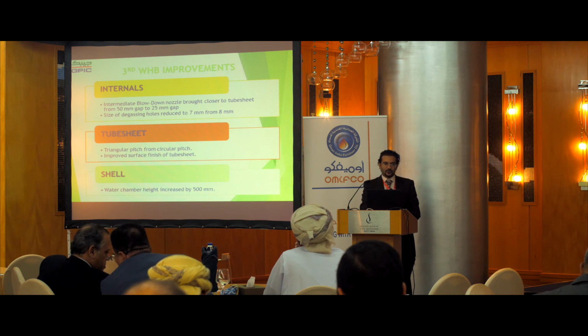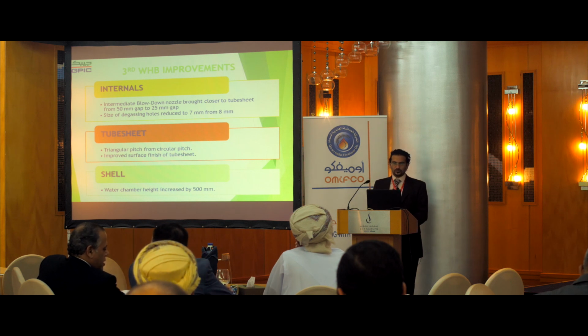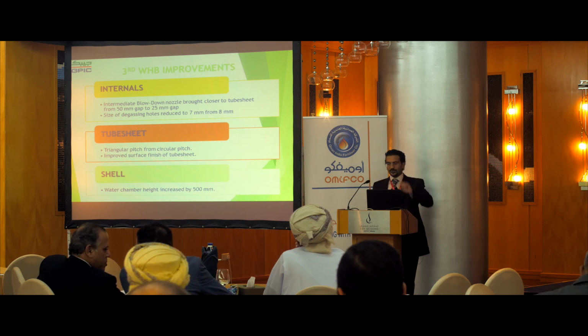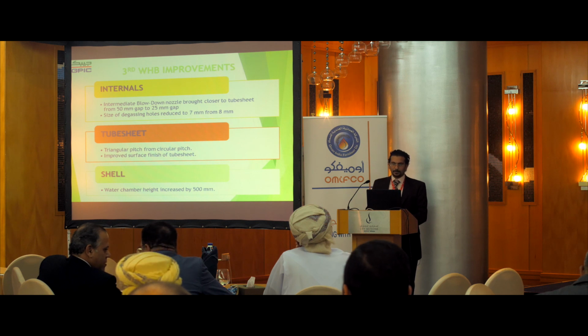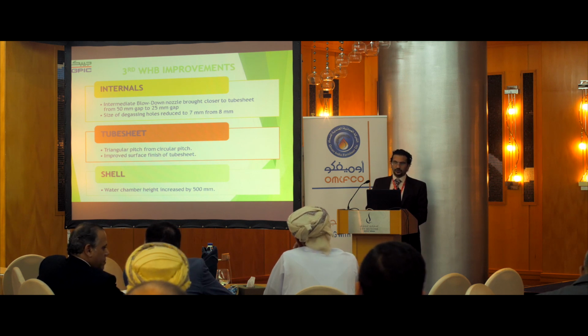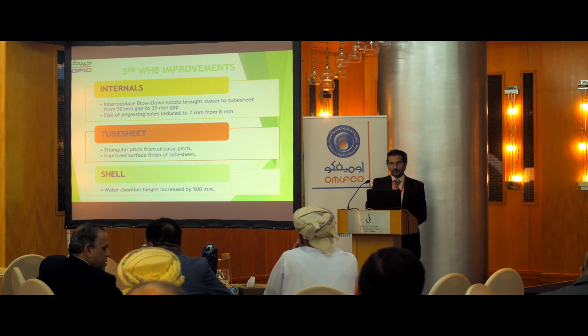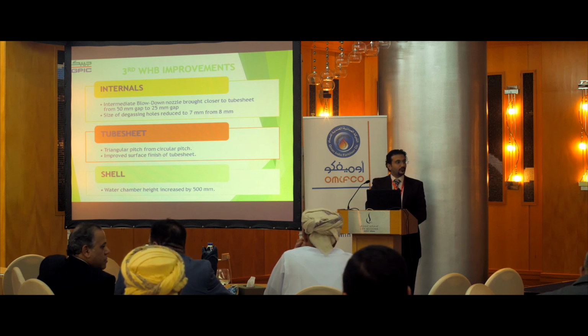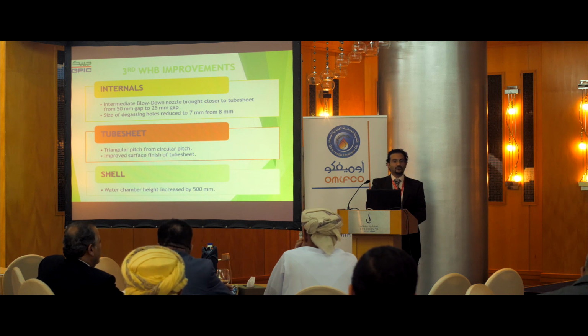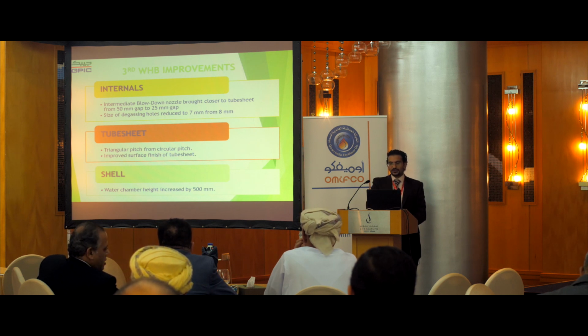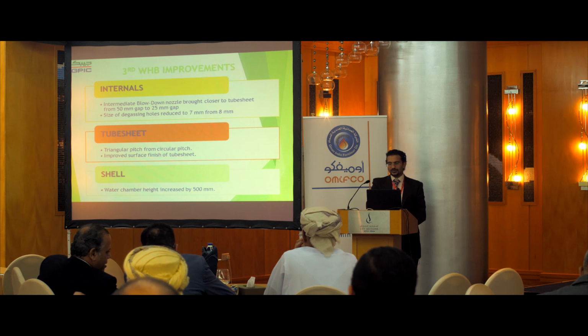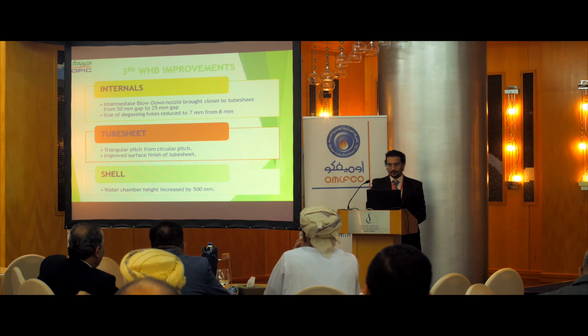For the third waste heat boiler, the improvements: the IBD, intermediate blowdown nozzle, was brought closer to the tube sheet, so there shouldn't be any collection of deposits in between. Size of the degassing holes was reduced to 7 mm from 8 mm. For the tube sheet, we chose to have the triangular pitch. It was better for our continuous blowdown, and improved the surface finish of the tube sheet, which means I think they did it in a smoother way.